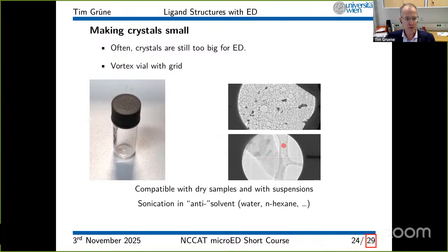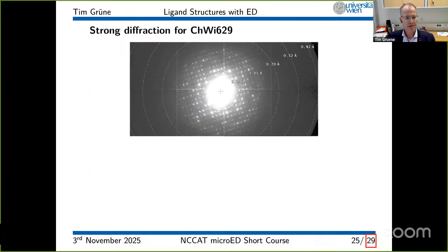An alternative to vortexing the dry sample is that you can also use any anti-solvent. That also applies to proteins. So if you have a protein drop with crystals, you can just vortex it a little bit, and then you get very small crystals. The diffraction, again, was super, super strong. You see here, this is 0.7 angstrom and even higher, even though the crystals were extremely thin and extremely flat. So again, with electron diffraction, you often get a surprise when you irradiate the crystals.